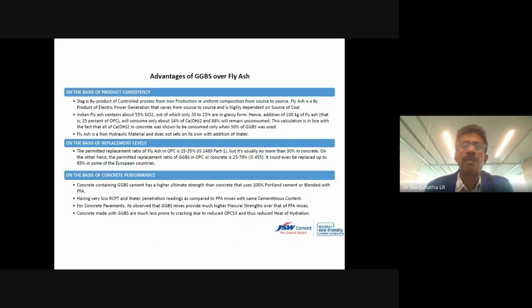So the advantages of GGBS over fly ash are many. It has a very good advantage because fly ash, as I told you, has very little amorphous content. Even though we have silicon dioxide, SiO2, at more than 50-55%, the reactive component is only about 25%. That is the thing.